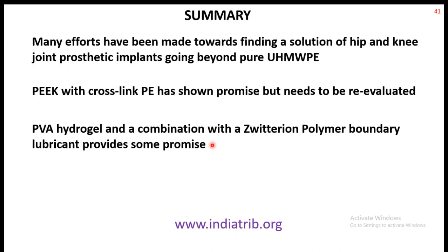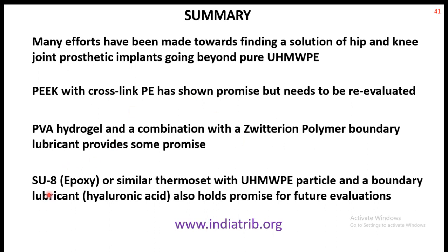PVA hydrogel, in combination with a zwitterionic polymer boundary lubrication, provides another promising material which is non-UHMWPE. From our research, we've found that epoxy or SU8, or similar thermoset with UHMWPE particles and a boundary lubricant, can hold another promise for future evaluation.